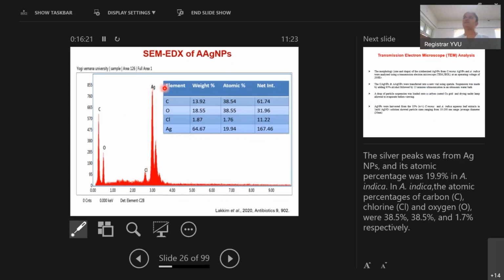This is the same EDAX of Azadirachta indica silver nanoparticles. The sharp peak represents the presence of silver. The silver net intensity is 167.46, atomic percentage 19.94, and weight percentage 64.67.